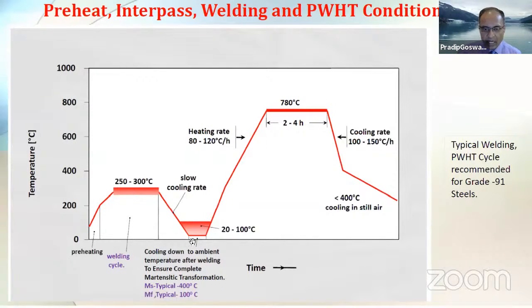Now, many times it happens that this is too short a time to do any kind of NDE or inspection on these alloys. So vendors may think, okay, let's do a full NDE or QA activity after the post-weld heat treatment. We'll talk about that later. But generally, from a good manufacturing or good quality assurance point of view, there should be one NDE step at this temperature. From this temperature onward, the alloy has to be heated to the post-weld heat treatment temperature.